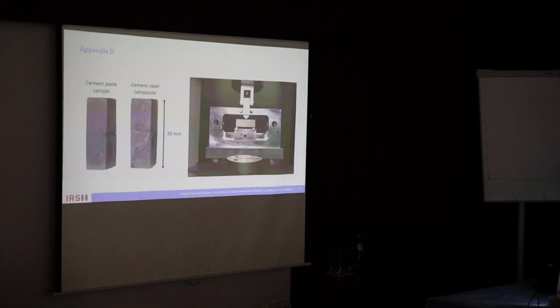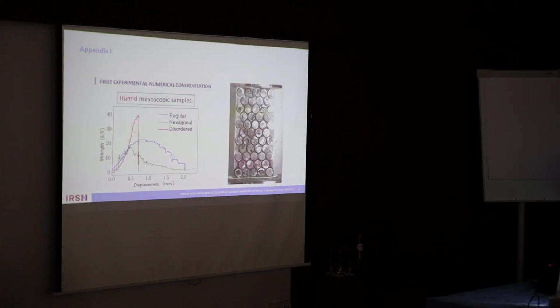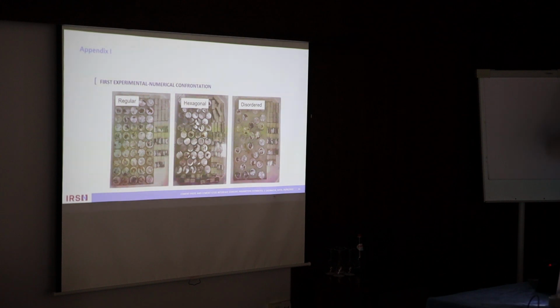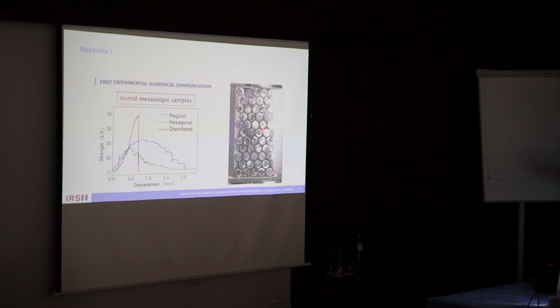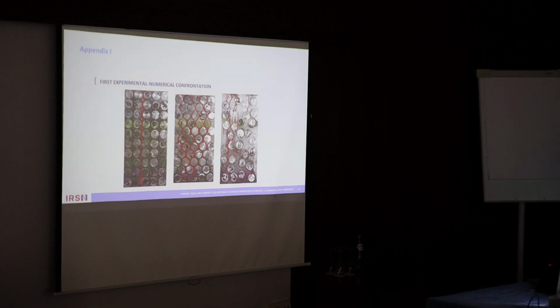At first we just use average values, but it was a topic I wanted to study during my PhD. And maybe we can see one result. So I've prepared three types of mesoscopic samples with different aggregate localization. And I performed the compressive test. And I compared numerical simulations. So I used the centimetric samples with a supervised test for estimating cohesive parameters, and then I used them on the numerical simulations. Here are the crack paths observed experimentally.